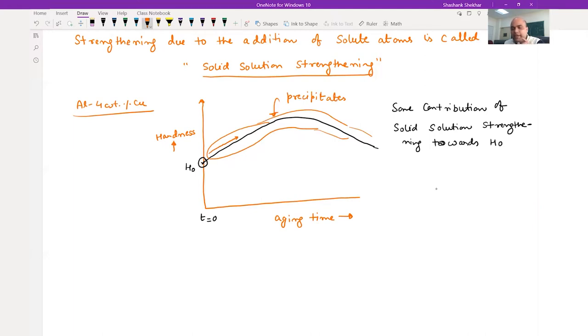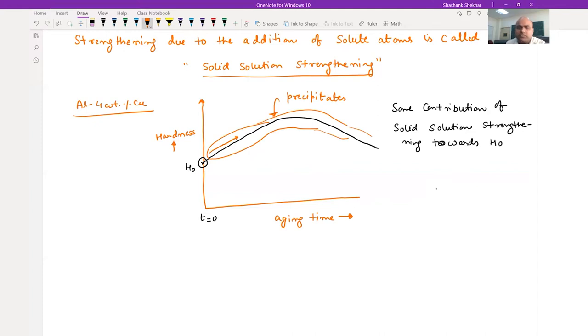Realize the difference between solid solution strengthening and precipitation strengthening. In precipitation strengthening, you have contribution from precipitates. In solid solution strengthening, you have contribution from the solutes present in the solid solution. The crystal structure of the solvent remains the same in a solid solution — like in aluminum 4% copper, the alpha phase is also FCC like aluminum. But precipitates like the theta phase can have a different crystal structure. AL₂Cu, the equilibrium precipitate formed in aluminum 4% copper, does not have FCC crystal structure. So a solute is an atom, while a precipitate is a phase — that is one key difference.